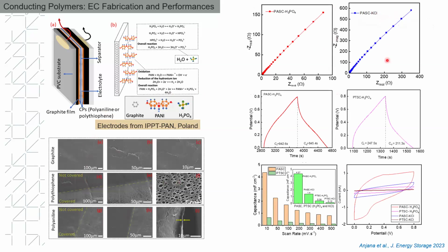For example, here you can see the electrodes for polyaniline and polythiophene based material, where for polyaniline with H3PO4, you can see the charging and discharging, where the Coulombic efficiency is much better compared to polythiophene. The performance also shows that polyaniline with H3PO4 gives a much higher capacitance compared to polythiophene. This is due to more redox reaction: in a conductive polymer, one is the conjugated polymer reaction, and another is the electrochemical double layer reaction, because of the conductivity of the polymer. Okay.